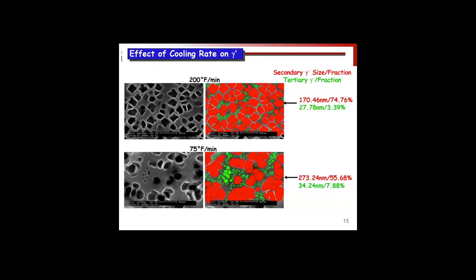The dislocations are hard to get through gamma prime, relatively easy through gamma, but there isn't a whole lot of gamma. The channels that the dislocations move through in the initial stages of creep are fairly small. So in primary creep, we start to fill all these channels with dislocations, and moving into secondary creep, we start to cut through all of these particles. Of course it happens sort of simultaneously, but that's just something to keep in mind - a good schematic.